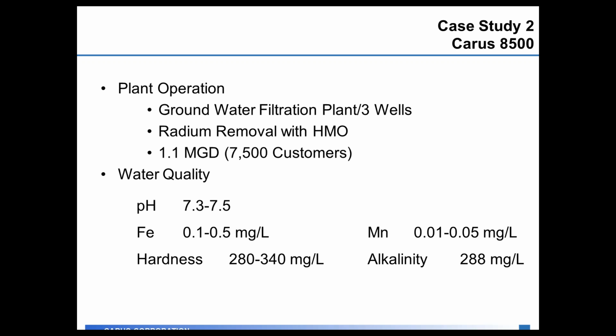They were a groundwater filtration plant, and they had 3 groundwater wells that they were going to treat. These plants were interesting because they had radium removal with HMO, or hydrous manganese oxides, in the plants. The plant was 1.1 MGD from these 3 wells, and they served 7,500 customers. When you looked at their water quality, the pH was 7.3 to 7.5 in the wells, iron of 0.1 to 0.5 milligrams per liter, which could be some of the cause of the red water issues in the distribution system because you're above the 0.3 milligrams per liter for iron. Hardness was 280 to 340 milligrams per liter, and the manganese was low at 0.01 to 0.05 milligrams per liter.